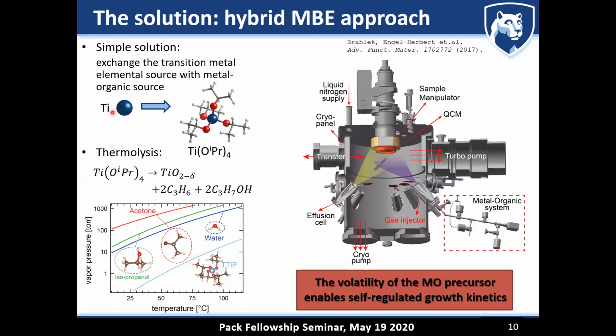So we just thought, okay, why don't we take elemental strontium, put it in the effusion cell, which is the MBE part, and we put the really well-working metal organic titanium tetraisopropoxide into a gas supply system, and try it this way. It turns out that the chemistry of this titanium tetraisopropoxide is so simple that you can buy hundreds of grams of it from chemical vendors, ready-made, for a couple of $100. Actually cheap. It's basically cheaper than if you would take high purity titanium metal. So this is the idea behind it. It's not that we are synthesizing these metal organic precursors. You can just buy them off the shelf. It is a very conventional product.